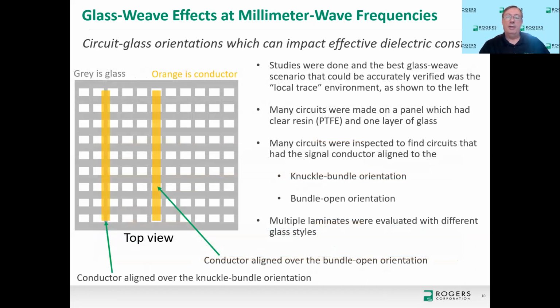So back on to the circuit glass weave orientation. In some of the studies we did, and I'm going to show you some data from these studies, we tried to do several different things. One, we tried to look at the periodic Dk trace environment, but unfortunately that's really difficult to verify accurately. But the local trace environment shown on the left, that's something we could very accurately verify and actually get circuits oriented to the glass exactly as we have shown here.